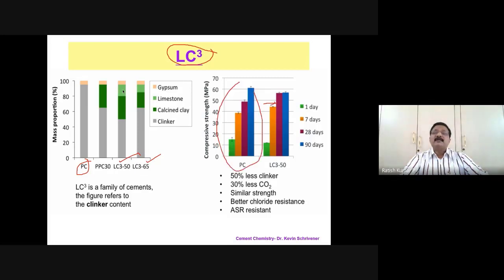Where is the Portland cement? These are Portland cement, and you can see within 28 days, by using a 50% replacement of the clinker with clay as well as calcined clay and the other material, you are able to get a good advantage, and it is already surpassing the amount of strength which you are getting in case of Portland cement, which means definitely the research on limestone calcined clay can still be continued. It also has better chloride resistance, and very good alkali silica reaction behavior. So what I mean to say at this point is 50% of the clinker can be substituted with limestone and calcined clay to get an equal benefit, or in fact a better benefit from the Portland cement. So that's a good alternative we can think about.